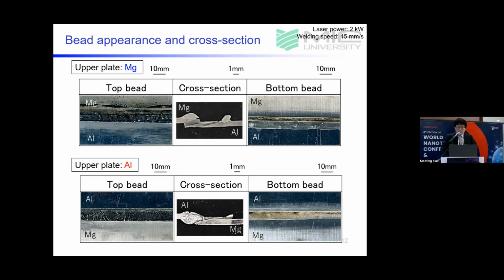Regarding the top bead, a pattern appeared on the bead as the place of the laser pressing, roller pressing through it. This pattern was more clearly observed in the condition with aluminum as the upper plate. When observing the joint cross-section in the center of the table, it can be observed that the upper plate has become thinner due to heating by the laser and pressure by the roller.